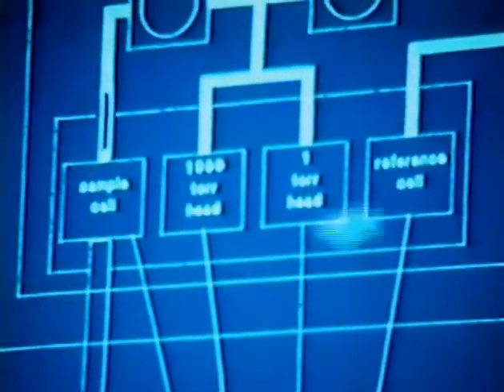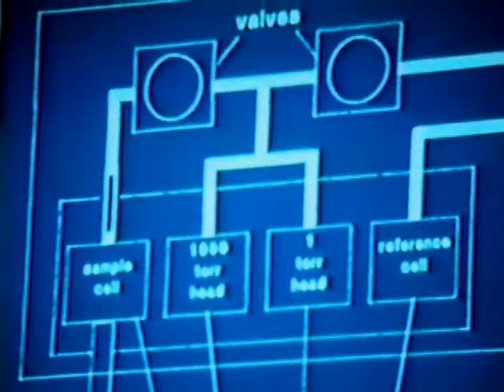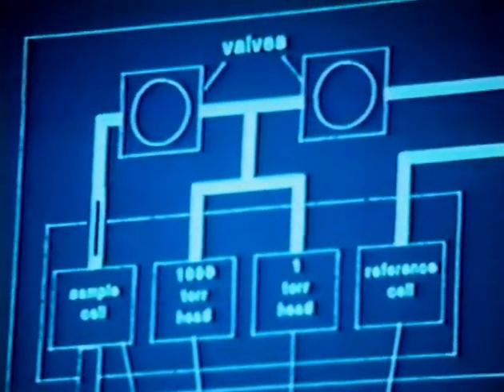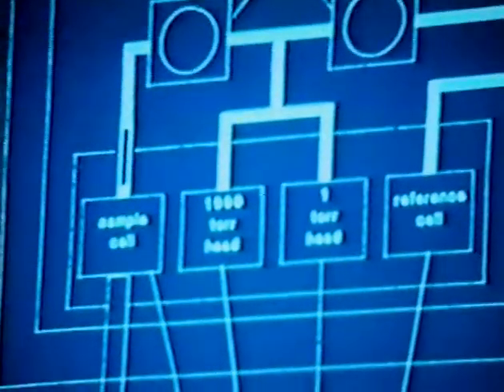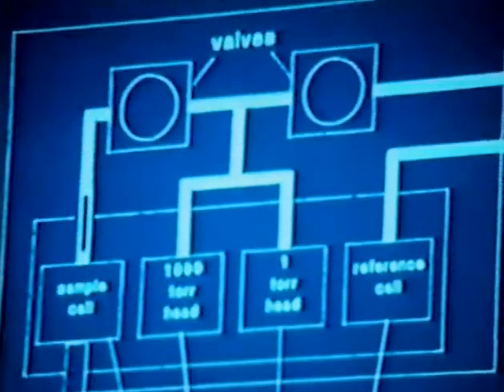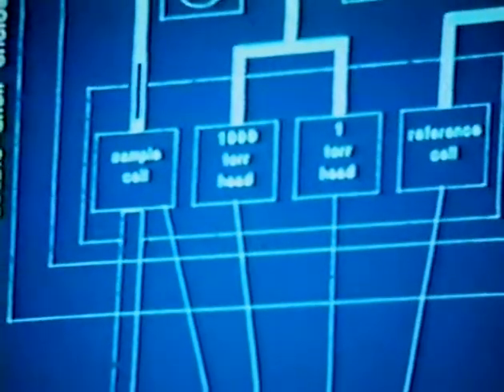Overhead view of the calorimeter, it's just a simple adsorption system. Our dosing volume is this piece in the center, and the reason that we can get these kinetic measurements is that we have incorporated Baratron capacitance manometers as part of the dosing volume, and therefore we can actually measure the change in pressure dynamically during a dose, and then look at the shape of the pressure trace curve and get an idea of the kinetics, qualitatively look at the changes in kinetics of adsorption as a function of coverage.